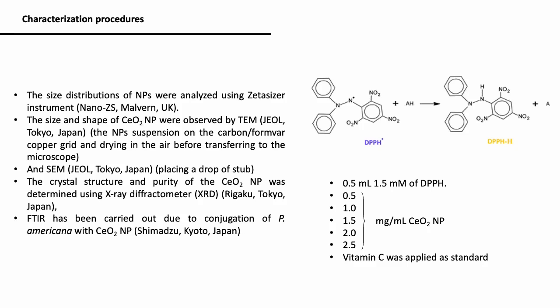DPPH free radical scavenging assay of nanoparticles was investigated. According to this protocol, 0.5 milliliter was continuously stirred with different concentrations of nanoparticles, as you can see in the slide. After being kept in an incubator for 20 minutes, the absorbance was examined by the spectrophotometer at a wavelength of 517 nanometers. In this experiment, vitamin C was applied as standard.